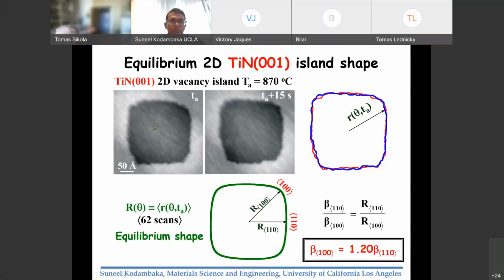Okay, so what we do is we first measure the shapes of the islands. And these are time-lapsed images. So from these individual contours obtained over a longer time, we then do an average shape of all these independent shape functions at any given time. You get the time averaged shape. And for 001, as you can see, the step edges, and in this particular case, it's rotated 45 degrees, and that's why you see these step orientations as written here. And we see the step energy anisotropy, and that is the ratio of the step energy 110 to 100 is basically the ratio of the radial lengths of these steps from the center of mass of the island.